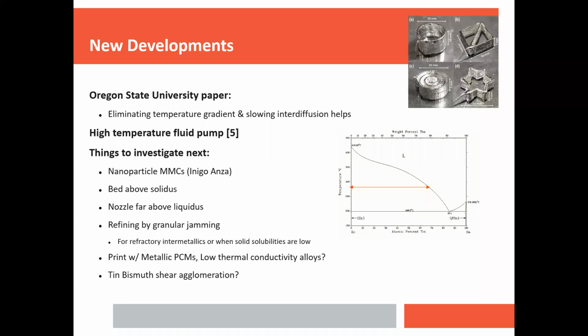Again, powder metallurgy has some fundamental issues as well with oxide inclusions, with potentially gas pockets and things. It really depends. The issues depend on the sintering parameters, but there's trade-offs throughout that. And if you can just lower the surface area that you're working with by extruding a wire from a metal melt, then you have to worry a lot less about oxidation and similar concerns, or even just pieces of binder pyrolyzing and getting stuck in the metal, things like that. Having the powder binder certainly reduces a lot of the issues associated with powder metallurgy, but it does not necessarily eliminate them.